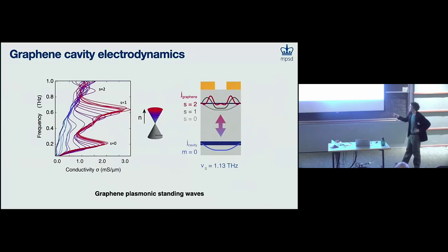What's interesting is if we fit this to just a Drude-Lorentz model, we can extract a mean free path for the carriers, and it's 10 microns. The size of the device is 10 microns, which shows that it's ballistic. And that's what's expected for an encapsulated graphene device. I don't think it has to be limited there, but this is what our data is showing, that the width is consistent with a 10 micron size device. So this may actually be a fundamental limit for this type of design. Does that answer your question somewhat?